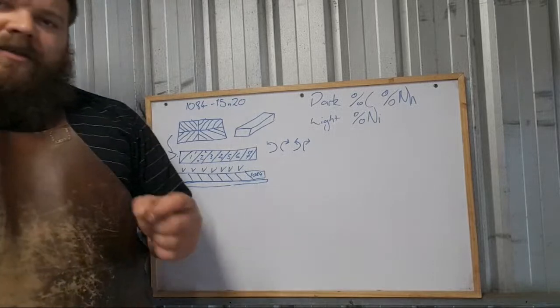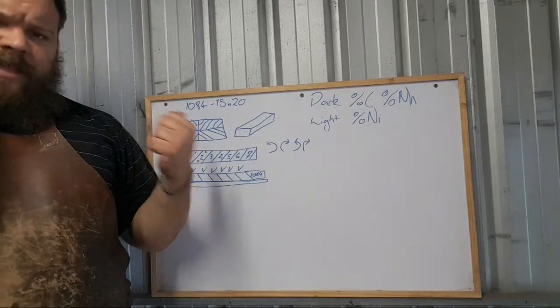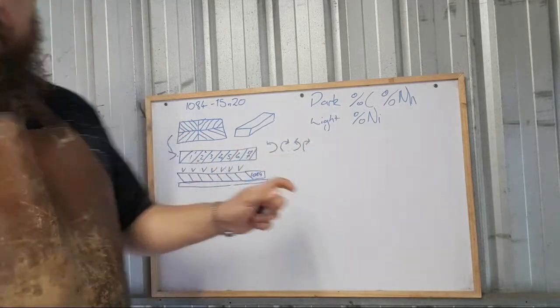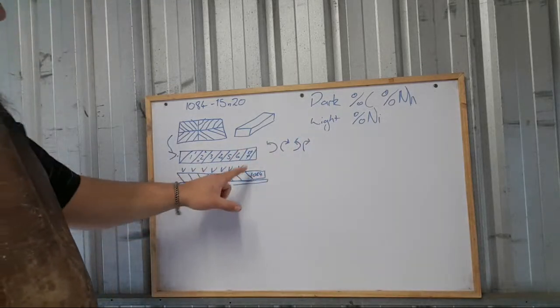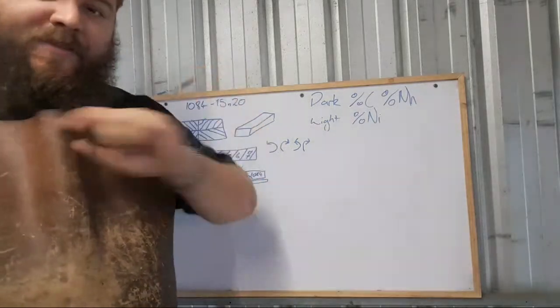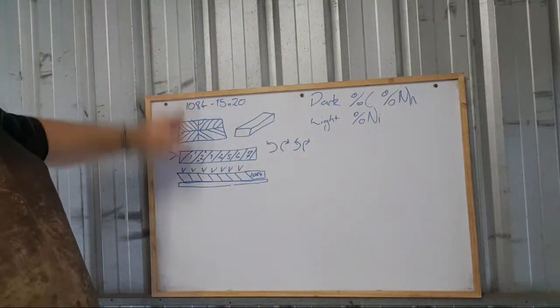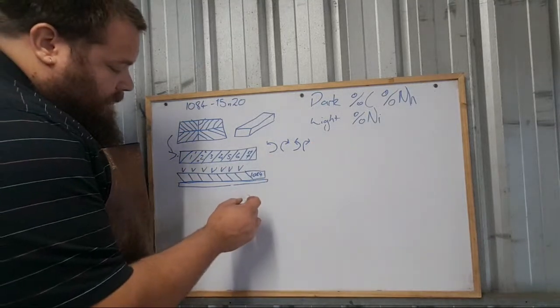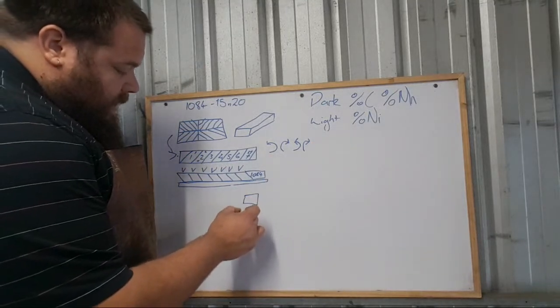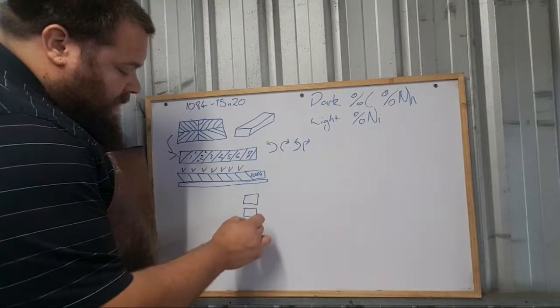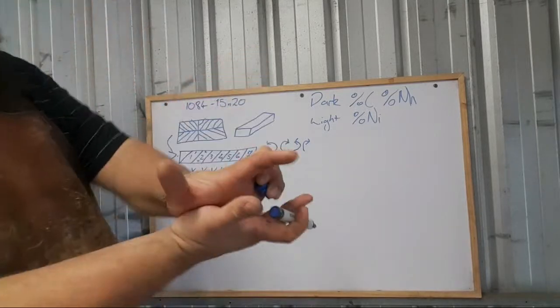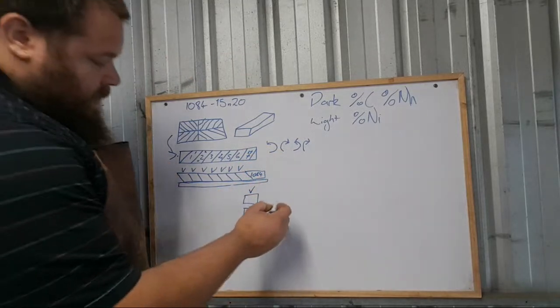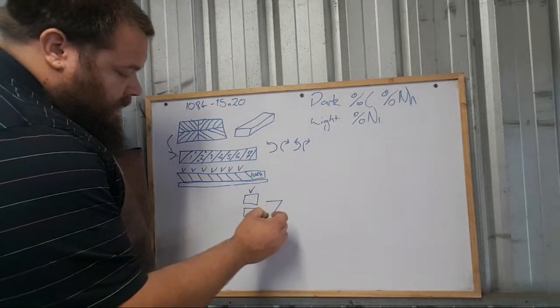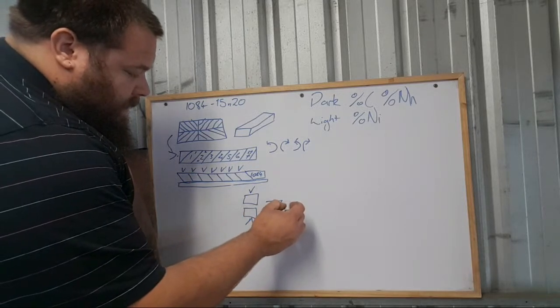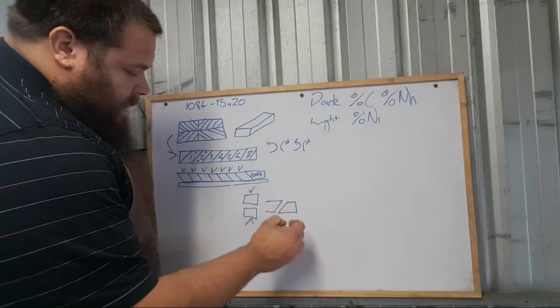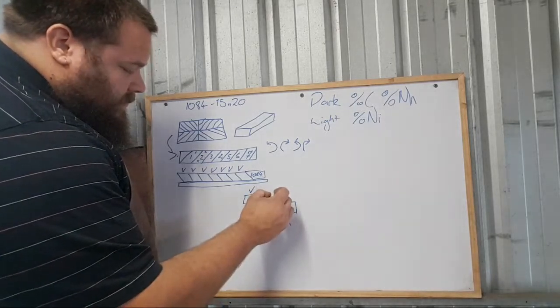It's not a weld that does well with borax, because the flux gets trapped inside these seams, and if the flux gets trapped in those seams, that's it, the weld's gone. Because you're putting a lot of shear stress on this. In a normal welding plane, you have one piece of material and another piece of material, and the force is dimensionally this way, right? You're just smashing them together. In this one, you have a piece of material with an angle on it, meeting another piece of material with an angle on it, but the force is still this way.